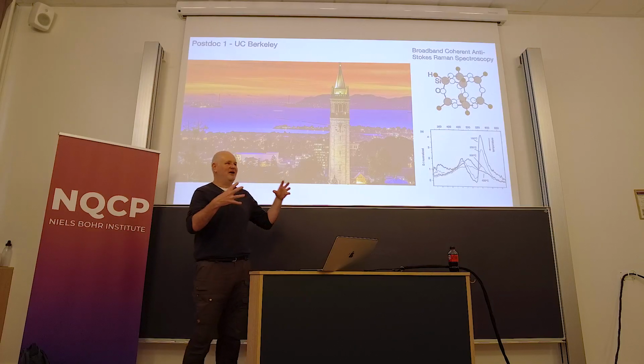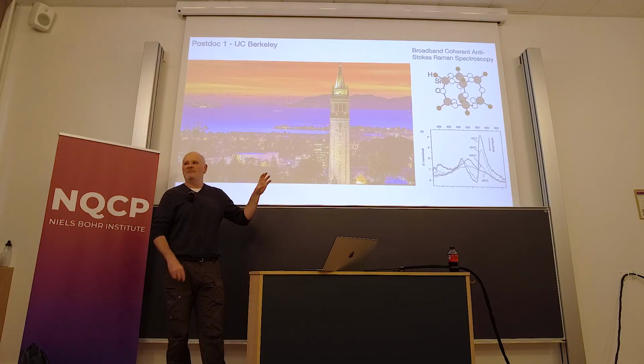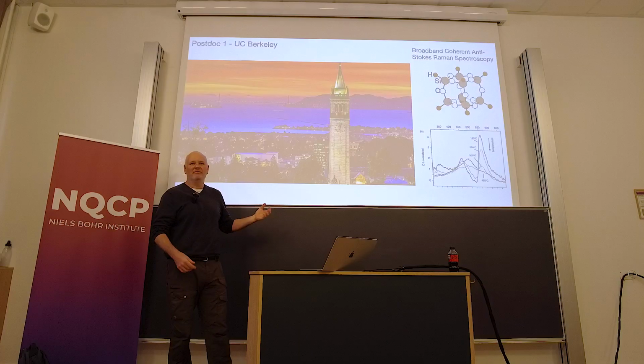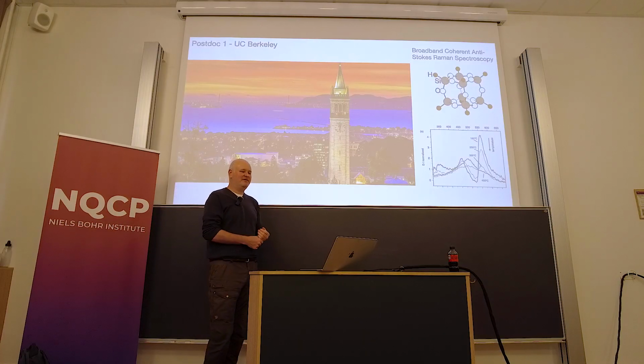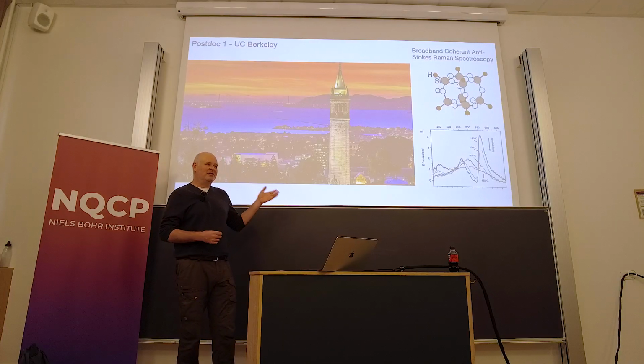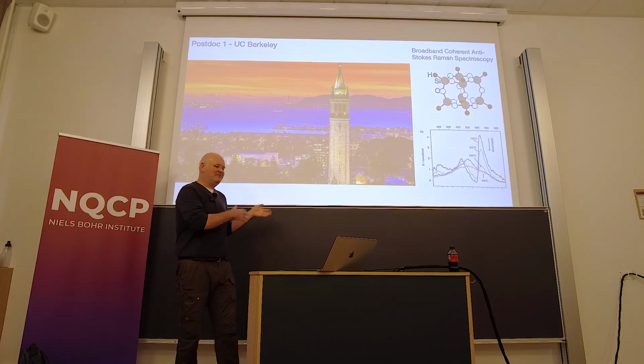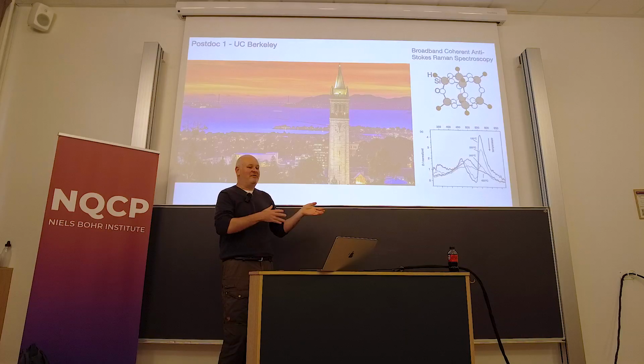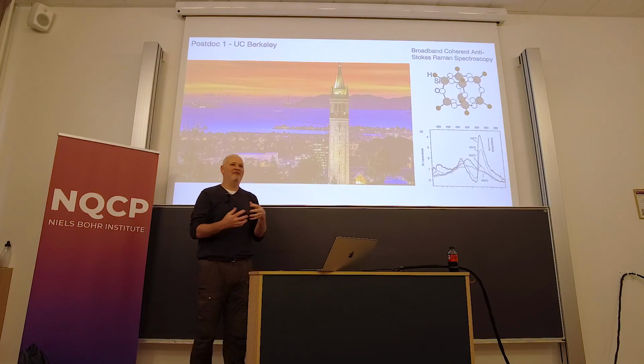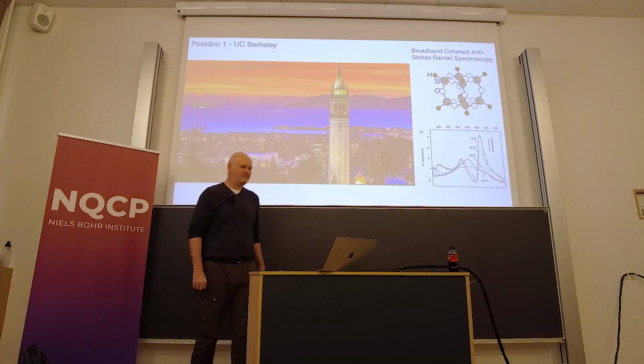Essentially, it's a cage of silicon and oxygen. It's more or less silica, but it's in liquid form. And so you can spin coat this onto surfaces, and it's used as a resist material for especially high resolution patterning. But it also is a particularly interesting material, one, spectroscopically, but two, you can learn things spectroscopically about how the material crosslinks, which informs how you can modify it to make it into a better resist.